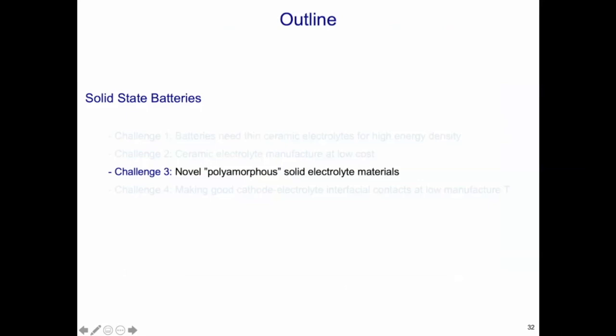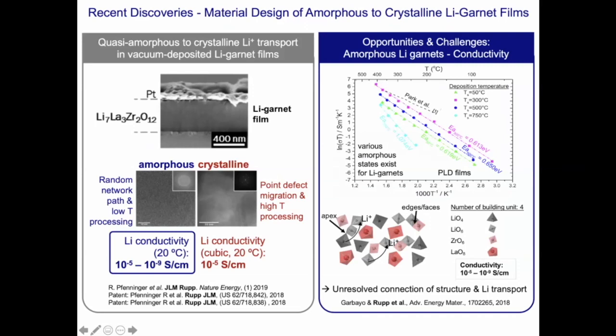So I want to show you here one more example, which is talking more about polyamorphous solid electrolyte materials. So when I showed you before the different structures, you could see that there is the option to make crystalline cubic lithium garnet structures. However, one could also see in the Raman spectrum and other indicators that it's possible to also make amorphous phases. And fundamentally, this is really interesting because imagine you could have a solid state battery electrolyte that has no grain boundaries. So in terms of lithium dendrites, this could be very attractive for some depositions.